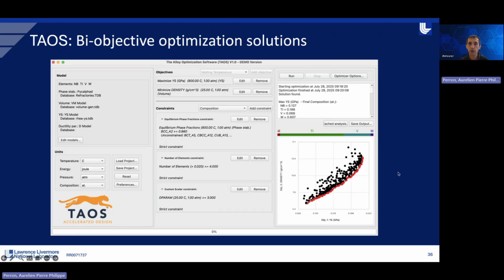So after, you can run your optimization and you can see that even within a 4 element space, the optimization went really quick. It takes less than 2 minutes, honestly. And it generates a Pareto front. So what it is, because now you have 2 targets, right? So you have a trade-off between your objectives. So we have density. Remember, we try to minimize density of the alloy, and we want to maximize yield strength on the x-axis. And so the red points here are your optimal or undominated solutions.